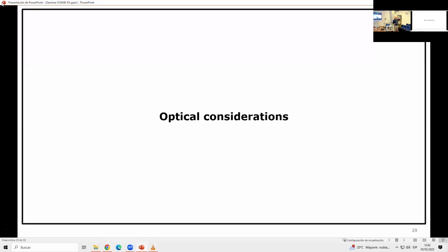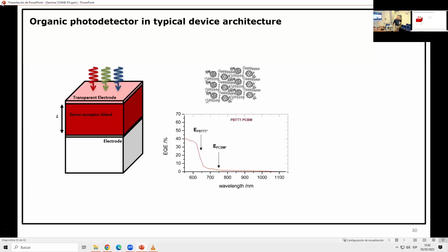For this PIN device, which I just told you about, all the layers in there are 50 nanometer, 100 nanometer, which is shorter than the wavelength of the light which is emitted or absorbed. So the total device thickness is about 200 nanometer, while the light it's emitting or absorbing is 500, 600, 800, 900. So that's a fun optical problem. You can't use just ray optics, you need to use wave optics. And with that, we have been playing a few years ago already.